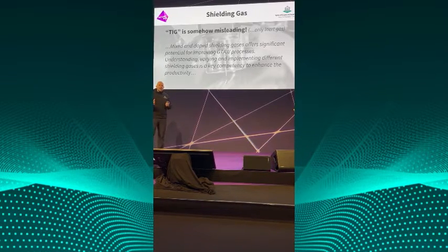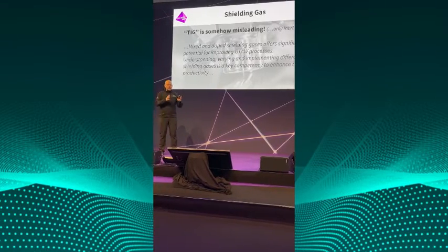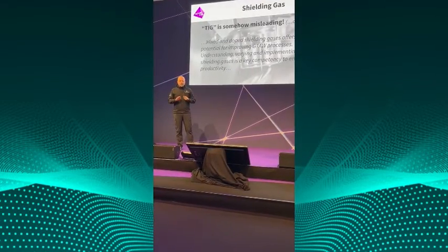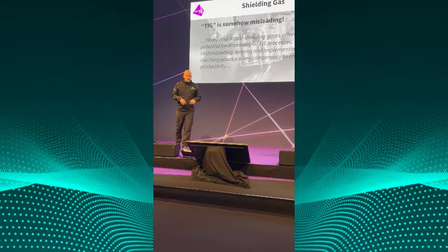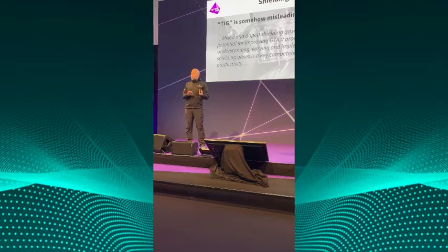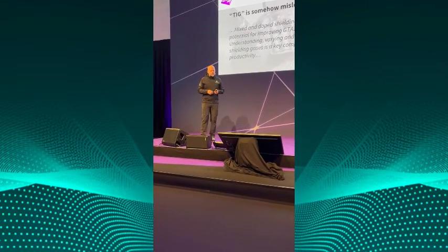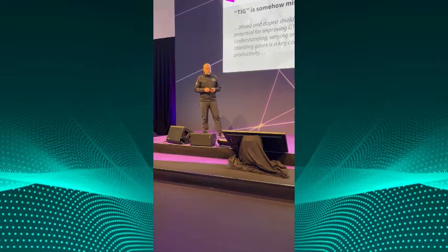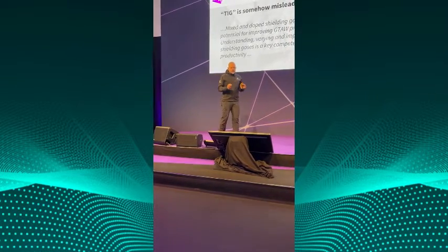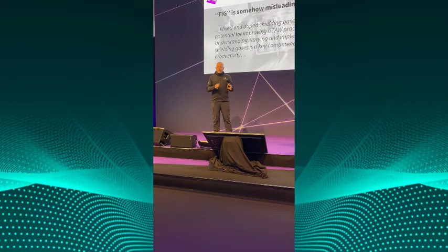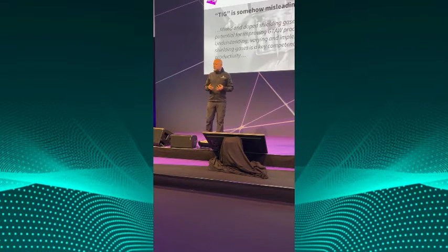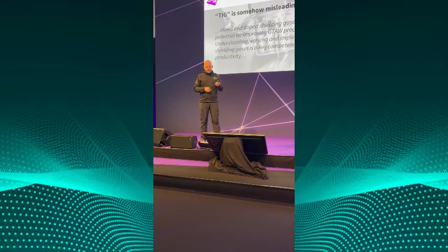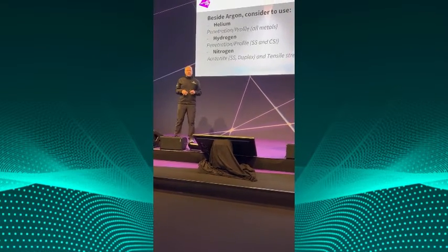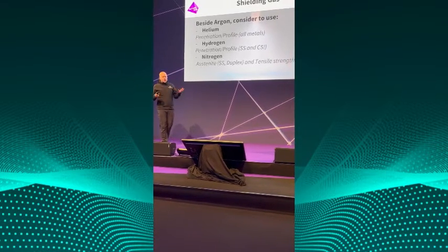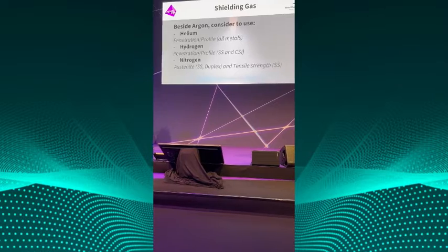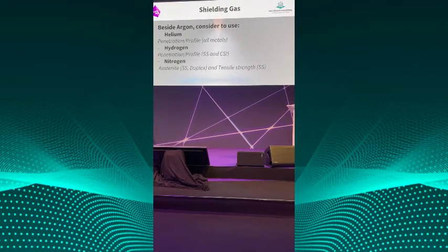So TIG is somehow misleading because it implies tungsten inert gas welding, but GTAW is more precise because we're not just using inert gases. So mixed and doped shielding gases offer a significant potential to improve GTAW processes. Hence, the understanding, varying, and implementing of different shielding gases is a key competence to increase productivity. So, besides standard argon, consider using helium, although it's a little bit rare, but you can do fantastic things which argon is just not capable of doing.